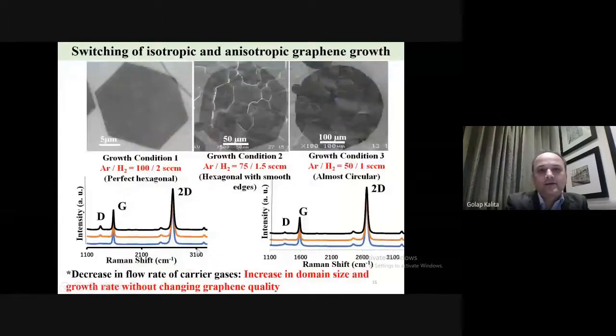So why does this type of growth happen in our CVD process? What we see is that when you have a high amount of gas flow with the precursor, say here argon is 100 SCCM and hydrogen is 2 SCCM, the precursor flows very fast on the substrate surface. So the interaction time of the substrate surface and the precursor is less. So in this case, we get hexagonal shape.